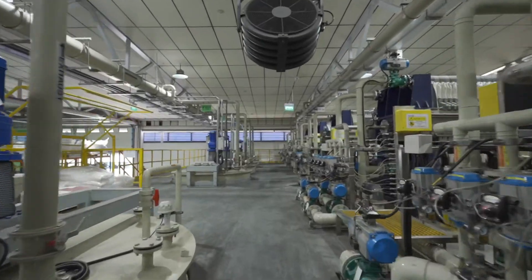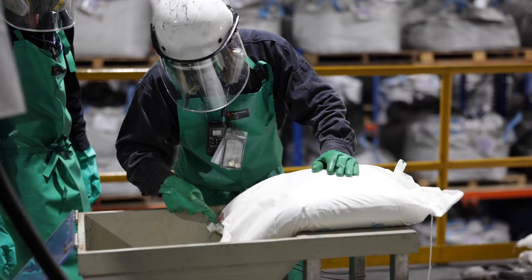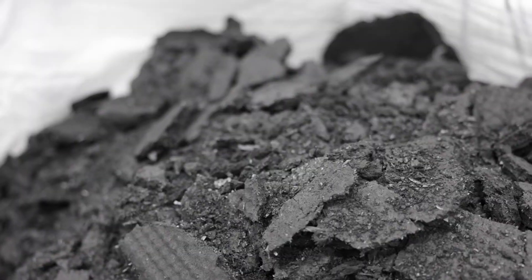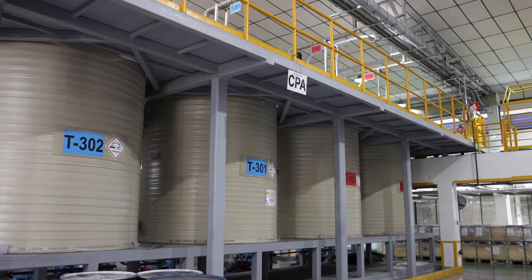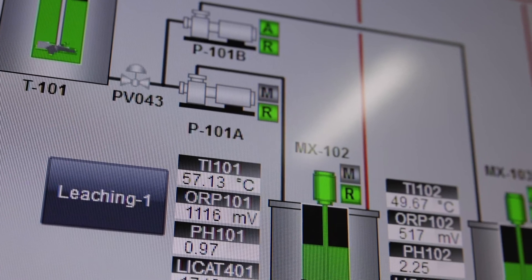Black mass is the starting point for the four-stage chemical process, which starts with leaching to extract the fine precious metal elements. It also includes several cycles of reaction and filtration, and produces graphite, cobalt hydroxide, and lithium carbonate materials ready for use downstream in manufacturing. All processes are highly automated.